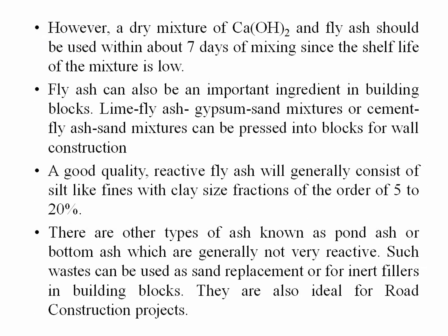However, a dry mixture of Ca(OH)2, that is calcium hydroxide, and fly ash should be used within about 7 days of mixing, since the shelf life of the mixture is low.